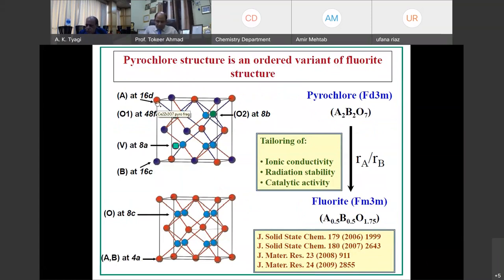If you swap A to B and B to A, you go from fully ordered to fully disordered. So in the pyrochlore structure, by playing with the Ra by Rb ratio, you can have tremendous control on the degree of disorder. And this particular property of the pyrochlore lattice, of enabling you to optimize the degree of order or disorder, is responsible for inducing different types of properties.